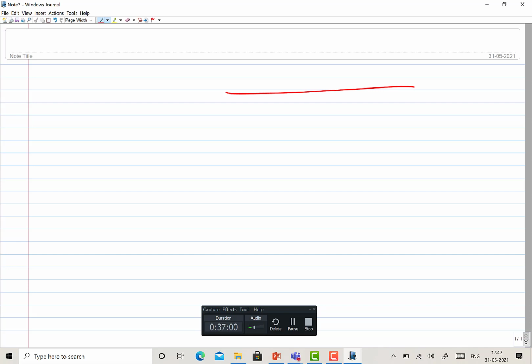This is one thing. Let's say this is the surface, and this is the zone from which material has been removed. When the material is removed by the shearing action, you will always see that the deformation has exceeded the fracture limit, where the ultimate shear stress level has been crossed. So that's why the shearing has happened. But below that, this region would have been subjected to first elastic deformation, then plastic deformation, and then subsequently removal through the shearing. But there will be a region below that that will be under elastic deformation only.